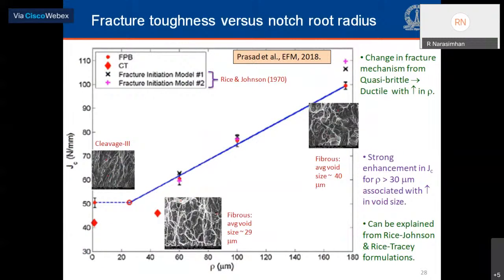Now let us take a look at the energy release rate, the notched fracture toughness versus the notch root radius. And I have also affixed the SEM fractographs so that we can correlate the toughness with the fracture mechanism. Beginning with the pre-cracked specimen on the left bottom, we note that this has failed by a cleavage type mechanism due to twin-induced cracks, and the toughness is low. As the notch root radius increases beyond about 30 microns, there is a transition to a fibrous mode of fracture, and the dimple size, as I noted, increases, and this is accompanied by a very large increase in the toughness.